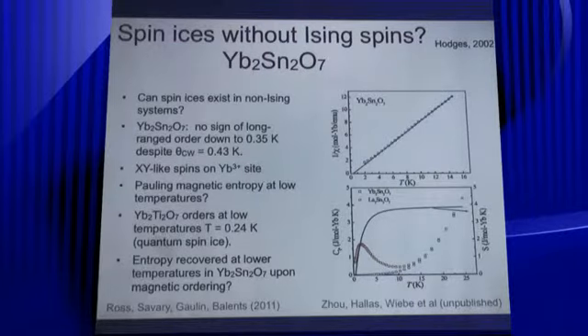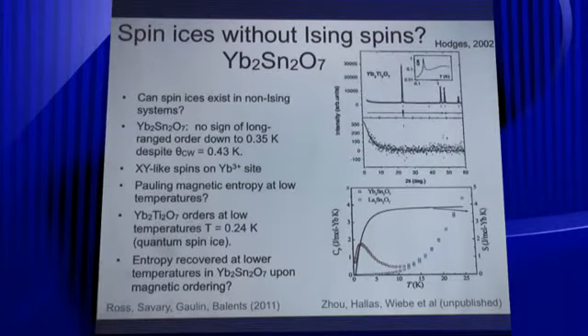So you have to, of course, look at, I'm not the only Canadian that can have cheesy flame effects. So if you look at ytterbium titanate, it has a very similar shape at low temperatures. But we've only measured down to here if you look at that scale. So there could be an ordering transition here. So you can be fooled by entropy. It's not a very good argument for looking for spin ices. You really need to combine various probes to look for this. So actually I expect there'll be a peak down here, and it'll have properties similar to ytterbium titanate. We'll look at this in more detail at low temperatures.